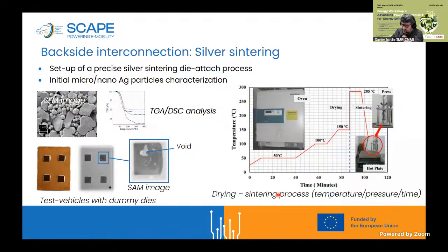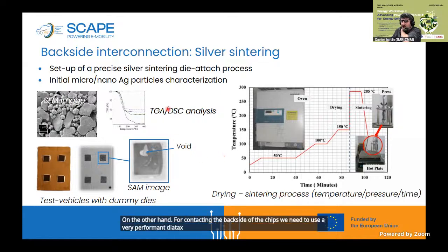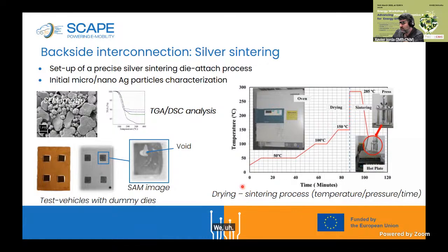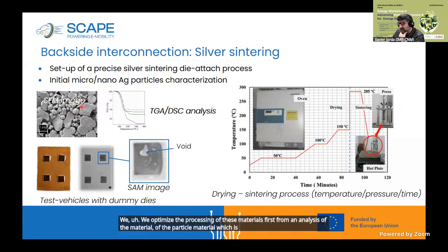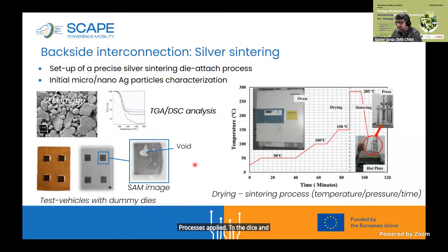On the other hand, for contacting the backside of the chips, we need to use a very performant die attach layer, which is based on silver sintering die attach processes. We optimized the processing of these materials first from an analysis of the material, of the starting material, which is based on silver micron and nanoparticles, and also on the optimization of the process, which consists basically of temperature, pressure, and time processes applied to the dies and to the silver sintering material.